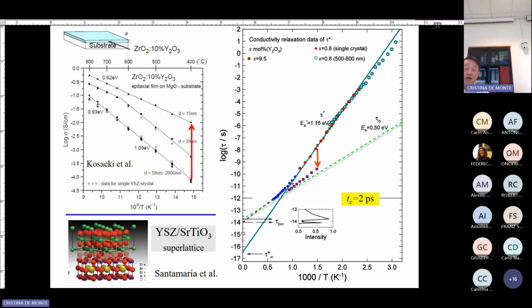So how can you understand this? You can't, because this is cooperativity. It's always abnormal, right? It gives you a large activation energy. When you go to the tau zero, you can understand the thin film, because now it's becoming non-cooperative. On the surface, they can move around freely. But also look at what this one does. It extrapolates down to 10 to the minus 13.7, almost the same as this attempt frequency. So you can understand why: simple physics from a non-cooperative, simple motion that has properties you can understand more easily.